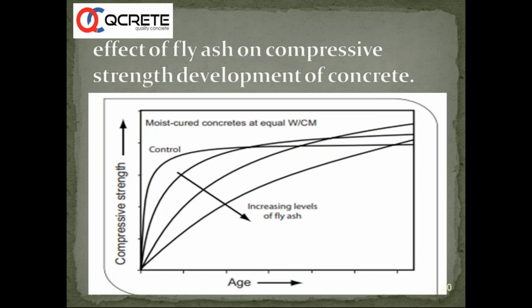Here we have another graph which talks about compressive strength versus age. Here, in the control graph, you can see that as the concrete is aging, the graph flattens, so the graph becomes parallel to the x-axis. Whereas with fly ash, initially the strength gains are lower and there will be strength buildup over a period of time. This graph is a representation of that. As we increase the percentage of fly ash, the long-term strengths go up and up, as we can see in this graph.